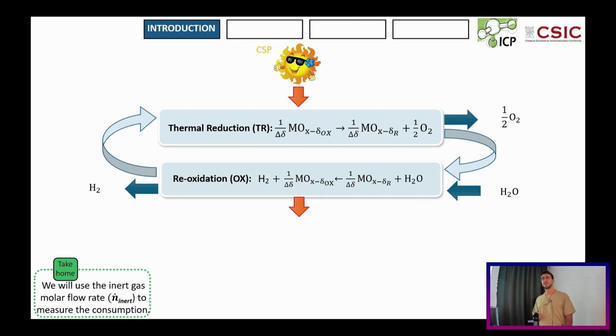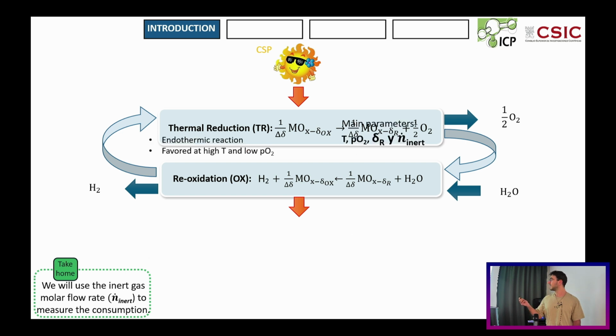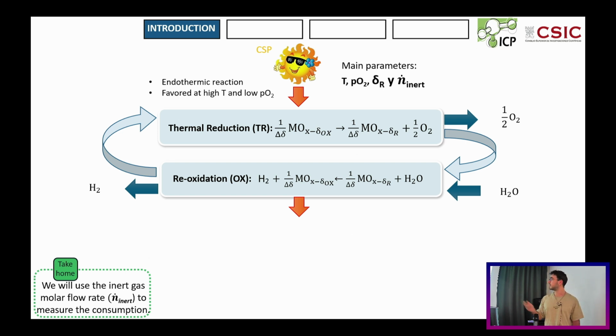One of the most important things to do when designing a solar plant is the system modeling. Specifically, we want to design the reactor part. For example, the reactor could hold a thermochemical water splitting cycle like that, which is a two-step cycle that uses a metal oxide, which is non-stoichiometric, to reduce the water molecule and produce hydrogen. The first step, we have the thermal reduction, which is an endothermic reaction favored at high temperatures and low partial pressure of oxygen.